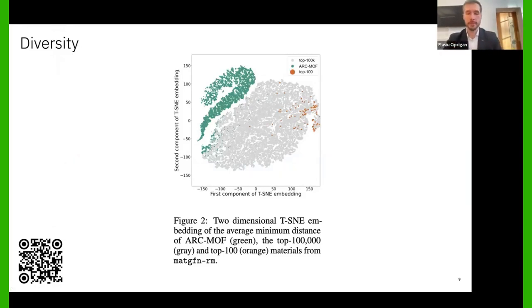So, as I've shown in a previous notebook, we've trained the GFlowNets and we've generated about 1 million candidates. Here, I plot the top 100,000 in gray and the top 100 in orange materials from what they call the matgfn-rm dataset of generated materials. In green, we have the materials in the ARC-MOF dataset, which is one of the reference datasets for metal organic frameworks. For plotting, we used the AMD invariant that Vitaly here and the team invented.